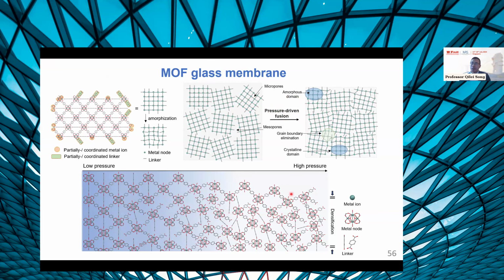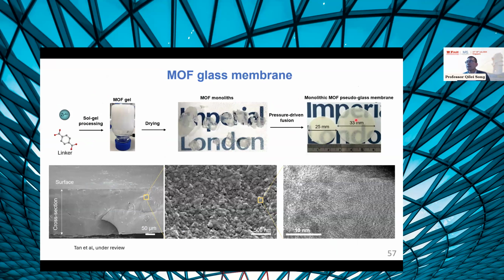The advantage is we were able to eliminate the grain boundaries in these MOF materials, and we get this kind of dense glass-like pellets. I call it MOF glass, but actually it's not purely MOF glass. It's a heterogeneous crystalline-amorphous MOF. This is a cross-section SEM image showing the MOF morphology. You can see it's a really dense membrane without any grain boundaries.